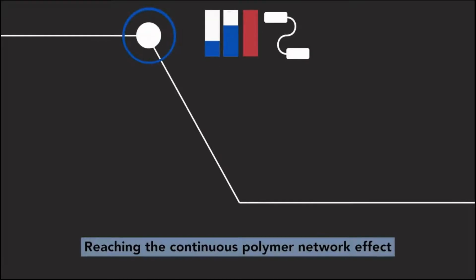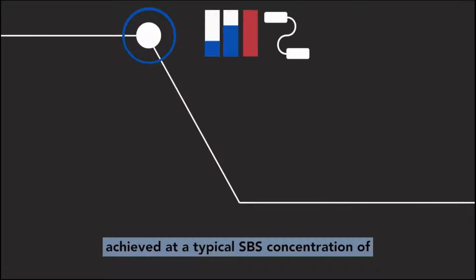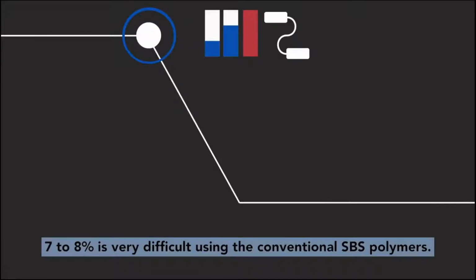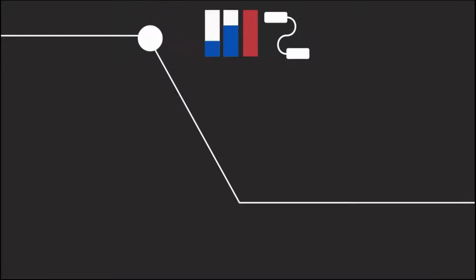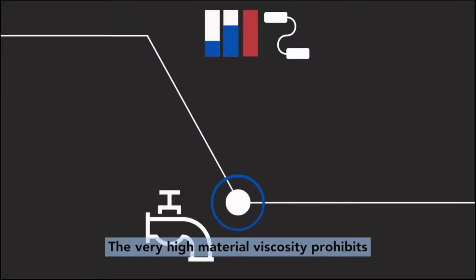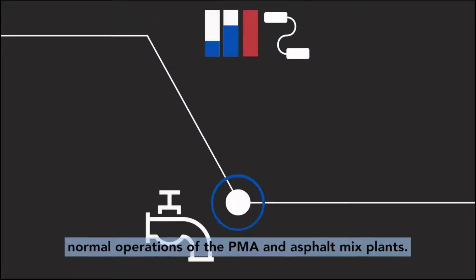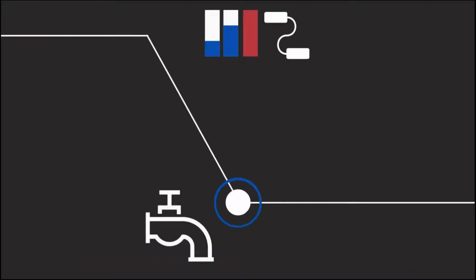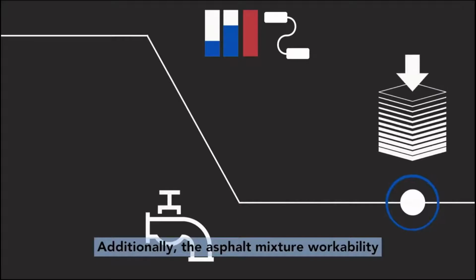Reaching the continuous polymer network effect, achieved at a typical SBS concentration of 7 to 8%, is very difficult using the conventional SBS polymers. The very high material viscosity prohibits normal operations of the PMA and asphalt mix plants. Additionally, the asphalt mixture workability becomes very challenging.